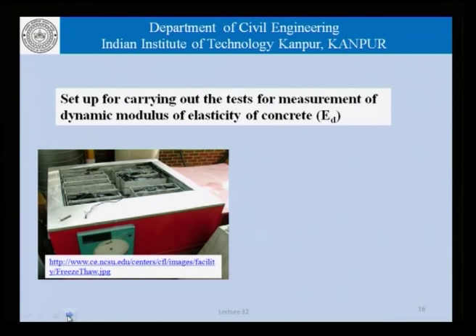This picture here shows how the specimens are tested in terms of exposure. These are some kind of boxes, and in these boxes we keep concrete prisms measuring a standard size, usually 10 centimeter by 10 centimeter by 40 centimeter. The entire chamber, with all the specimens in it, is subjected to cyclic freezing and thawing by having a fluid here, and the temperature of that fluid is varied between two extremes. The temperature cycle is fixed as far as the standard is concerned: we know the maximum temperature, the minimum temperature and the durations of the cycles, and therefore we can define the number of cycles of temperature variation we are carrying out.